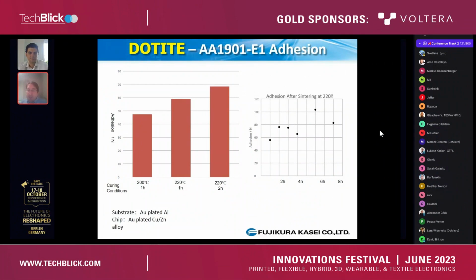Like many of our electrically conductive materials, AA1901E1 performs slightly better when cured for longer and at higher temperatures, and you can see how adjusting the sintering conditions from 200 degrees for 1 hour up to 220 degrees for 2 hours can improve the adhesion. We even have some data for sintering up to 8 hours, so we don't really expect anyone to do that, but you can see how it improves the performance. Okay, next slide.